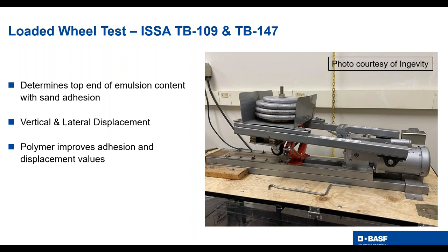And realistically, I know many of you have heard about balanced mix designs. Really though, slurries were the first true balanced mix designs. You had the loaded wheel test, the ISSA TB109, TB147, that you determine the top end of the emulsion content with sand adhesion. So that was very important. And with some of the microsurfacing applications, you now have the other TB that you measure vertical and lateral displacement. That just shows that it has some of that fatigue resistance that you're looking for. This works extremely well to get the top end of the emulsion content for these slurry microsurfacing mixes. So it does a very good job.